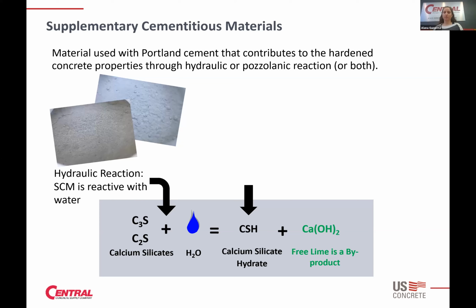And what you get as a result of that is something that we call CSH, calcium silicate hydrate, which is going to be that strong paste product that's holding everything together. It's holding the rock and the sand and all the powders. And that chemical reaction is what makes it go from a liquid state to a hard concrete and build strength and the density of that material. A byproduct of that reaction that's also mixed in with that paste is free lime or calcium hydroxide.